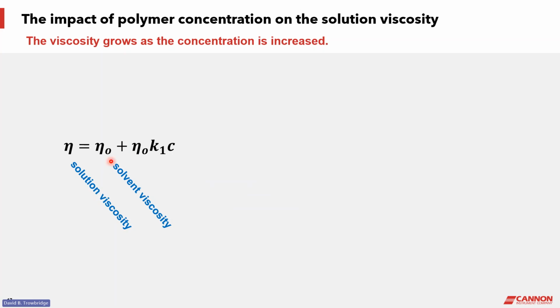So it's a combination of the solvent viscosity and this term here that includes the solvent viscosity, but it's increased by a factor and by the concentration. And it's going to represent an increasing number of deformations that we're sensing as we increase the concentration. And if we increase the concentration, we're going to be dealing now with interactions between the polymers. They're starting to influence one another at higher concentrations, and another term is required, and this term carries even more weight on the concentration because it's squared. And another term, this time cubed, is going to start to take into account actual physical contacts and overlaps with the polymer molecules.